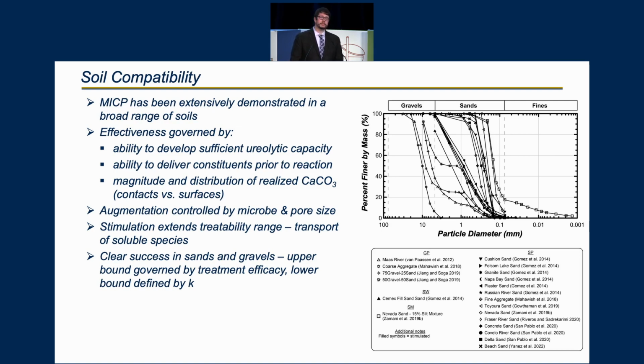For augmentation, treatability or treatment success is largely controlled by the compatibility between bacterial cell size as well as soil pore size, which can limit cell transport, particularly once pores become exceedingly small to pass cells through. Stimulation instead may extend this range, really requiring only the transport of soluble reactant species, and certainly we think that this might make it more effective in finer materials.